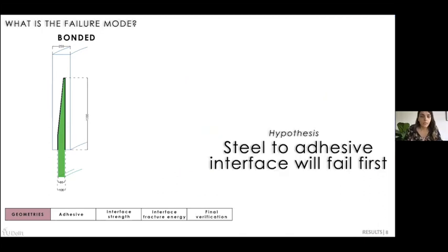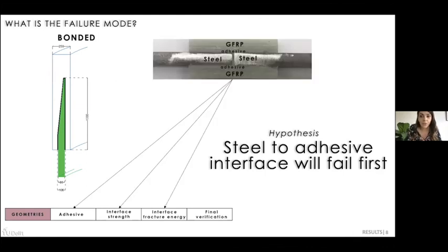Starting with the bonded joint, the first question that came to my mind was, which failure mode is to be expected? I made a hypothesis that the steel to adhesive interface will fail first, and I had to somehow check that. So I switched to a much smaller and thus easier to test specimen. It's a double lap joint with steel adherents being the inner ones, and GFRP as outer adherents.